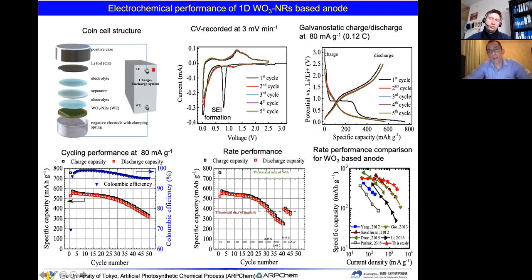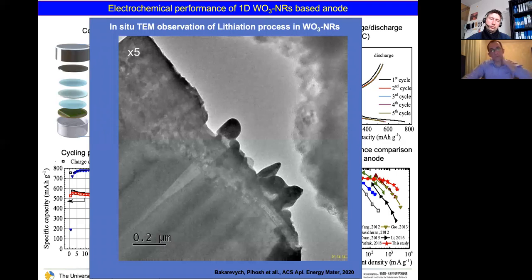And if you compare the other material with already published ones, this material shows very nice specific capacity and also lifetime. Okay, and this is the last result, which Dr. Roman Bakarevich recorded. So this is the in situ TEM analysis, how our nanorod absorbs lithium ion and how it expands.